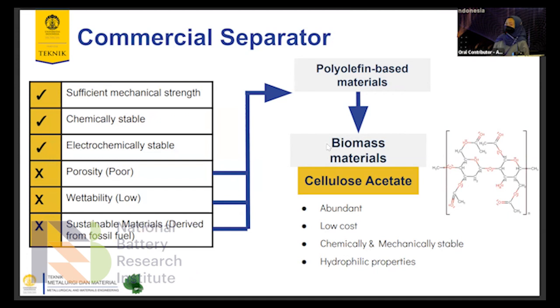There is a commercial separator these days, which has sufficient mechanical strength, and is chemically and electrochemically stable. However, it has low porosity and wettability, and it is not a sustainable material because it is derived from fossil fuel. So we need a solution to overcome these problems. One solution is using biomass materials because of their plentiful availability in this world, specifically in Indonesia. One of the biomass materials is cellulose acetate, and cellulose acetate is also abundant and low cost, also chemically and mechanically stable, and it has hydrophilic properties because of the presence of hydroxyl and carbonyl groups.